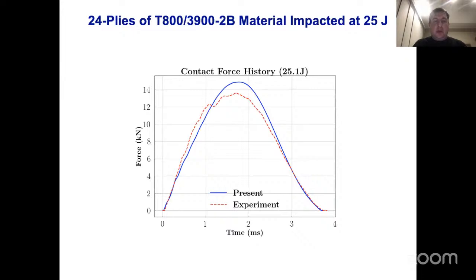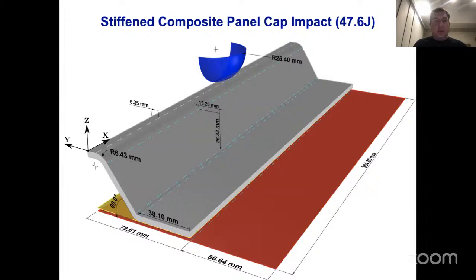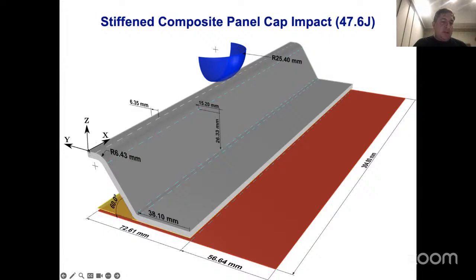Here is a contact force history, and the matching is okay. No data on the dents were reported in this case. And so, the final impact example I want to show you is an impact on a stiffened composite panel at 50 joules. You have the plate or the panel, you have the stiffener sitting on top, and the stiffener actually has 16 layers of CFRP. And the geometry is given here.